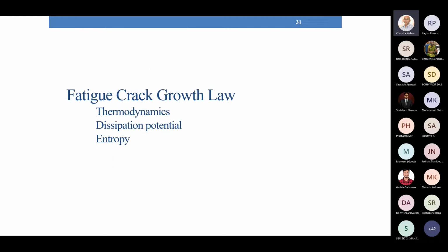So let me next go to how we make use of these experimental results in developing a fatigue crack propagation law. People have used the Paris law, the modified versions of it, and they have obtained many empirical relationships. But what we thought is we now have a good set of experimental data. So why not use, because we see that the energy dissipation takes place, thermodynamics, the best subject to apply for fatigue crack propagation, through what is known as the dissipation potential and entropy.